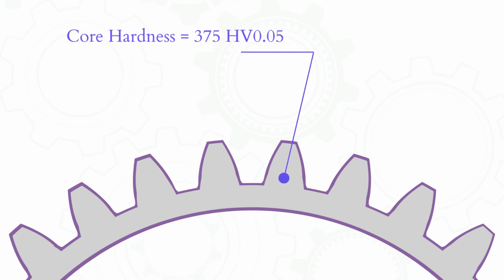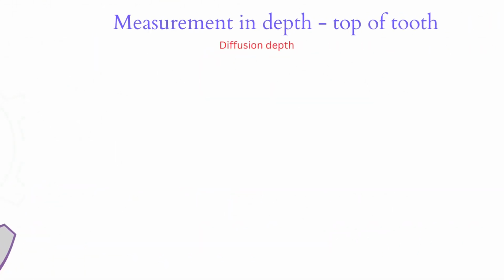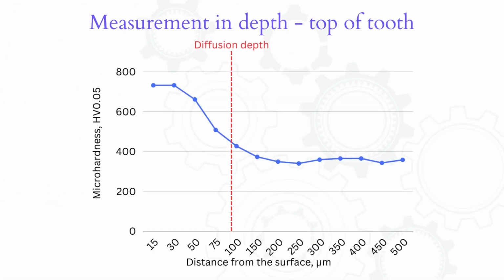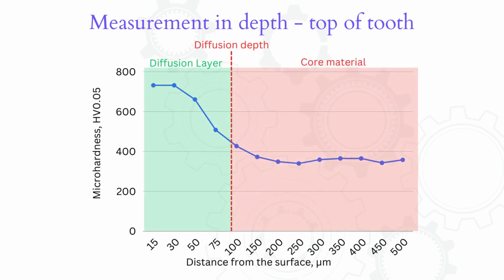We are lowering the load to 50 grams, because we want to be more precise in the measurement in depth. Now, we are going to measure the hardness in depth, starting from top of the tooth and going down, towards the core. We are going to do the same in-depth measurements between the teeth. A few measurements are done for each place in order to confirm the results are uniform. By doing this, we are going to get a graph of the hardness in depth. Going further away from the surface, we will be measuring in places with less diffused nitrogen, which means less hardness, until we reach the core hardness. And this way we can determine up to where the nitrogen diffusion layer ends.